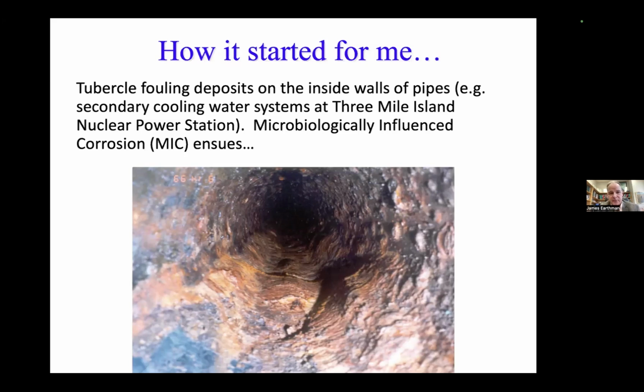Three Mile Island is actually on a river, and they bring in water from the river and use it in their secondary cooling water system, which cools the primary system, which has pristine treated water, very clean water that goes into the nuclear part of the plant. But that system has to be cooled by the secondary system, and it just has coarse filtered river water. And these tubercles can form on the pipes in that secondary system. And once they form, they are very tenacious.